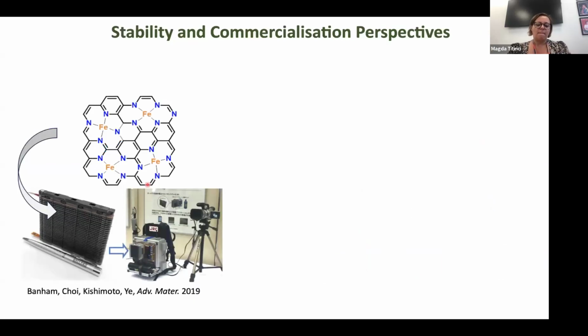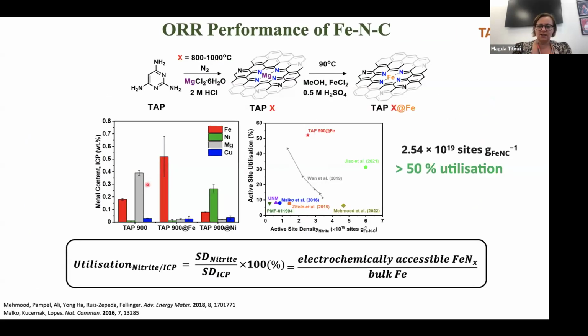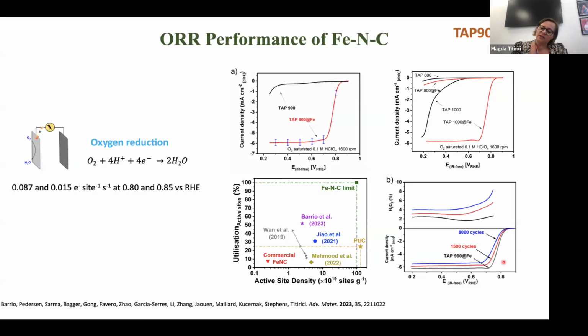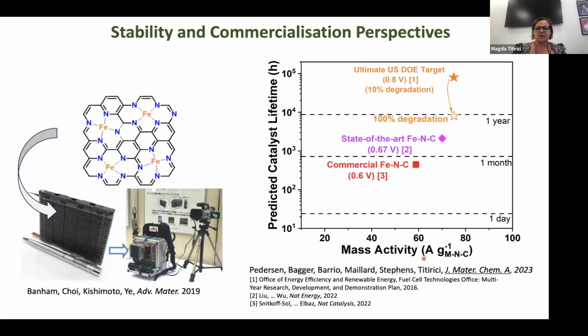And then to end up the oxygen reduction reaction, I will not give you details, but it's not easy, but we could make the single atom catalyst work very well for the oxygen reduction reaction, similar to platinum. But already if you look here, this is the initial cycle, and after 1,500 cycles, this starts degrading, so the current is decreasing. And so the problem with this catalyst is that they're not very stable under the real operating conditions that you have in a fuel cell.